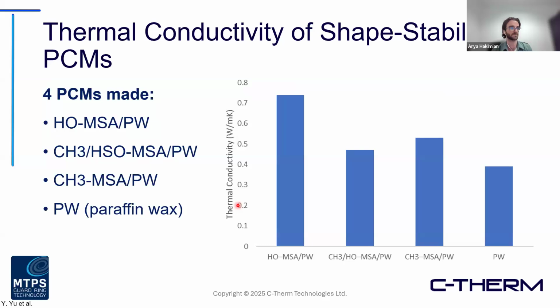And here, just kind of highlighting some of the results. So they were comparing their materials against a pure paraffin wax, different materials, different additives inside of their mixture. Again, kind of seeing the different trends, your highest performer versus the lowest performer. Depending, again, if you're looking to achieve a high or low thermal conductivity, you can use these types of measurements to, of course, baseline your performance and then see how your addition or modifications are getting you closer to that goal, or perhaps in some cases further away. But it's important to be able to actually test for that, of course, right? So we can really get that direct measurement data to understand if we are going the right direction or not.